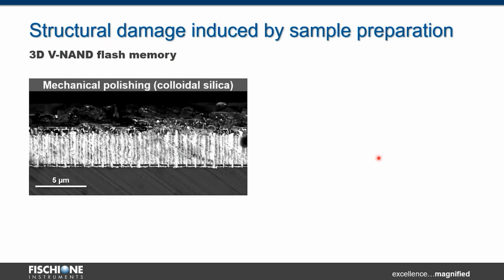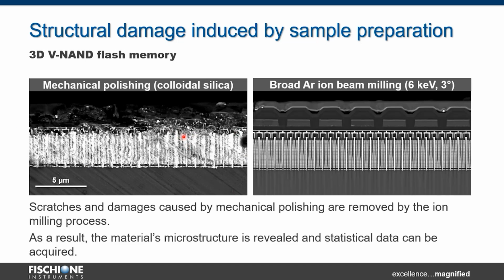Here we have some examples of sample preparation by different techniques and then broad argon ion milling. Here we have a flash memory, a VNAND flash memory, as you can see. The sample preparation was attempted by mechanical polishing, and as you can see, all the structure of the sample is destroyed. We have a lot of scratches and we see practically nothing on that sample. When the same sample is prepared by broad argon ion milling, it removes all that scratching, all that damage, and exposes a nice, beautiful cross-section